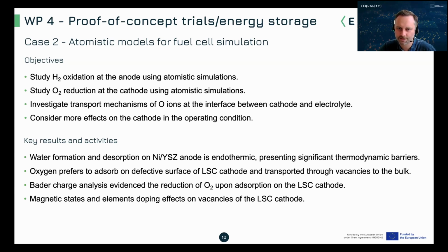Then to investigate the transport mechanism of oxygen ions in the interface between cathode and electrolyte, and also to consider some more effects on the cathode in operating conditions. Key results and activities were that the water formation and desorption on the nickel YSZ anode is endothermic, presenting a significant thermodynamic barrier.